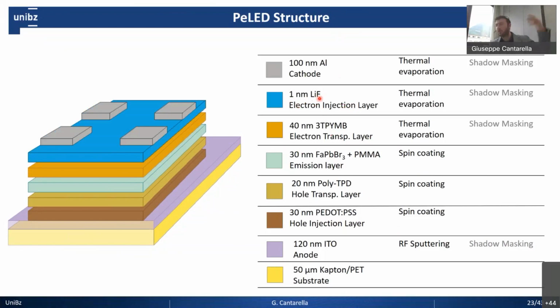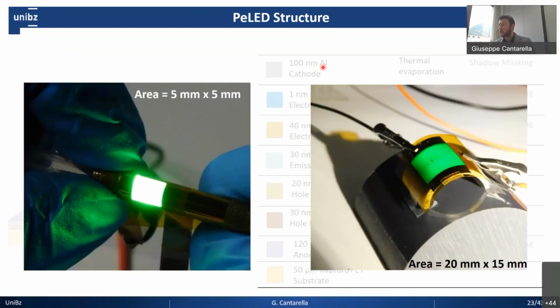And the last part is the second contact that we did by evaporation with aluminum, with 100 nanometer of aluminum. The result, as you can see here, and that's what we aim for, were LEDs, so devices that could be even in the millimeter or even centimeter square area. So what you see here, for example, is an LED which is 5 millimeter by 5 millimeter. As I was saying before, it is emitting in the green region, but we also went further up in terms of area and surface. And what you have here is a 2 centimeter by 1.5 centimeter LED, shining on a curvy surface.